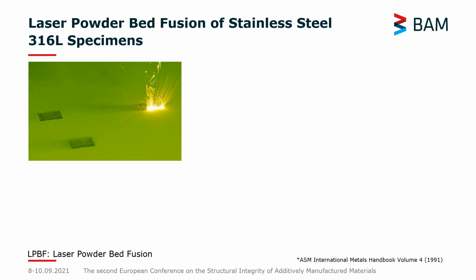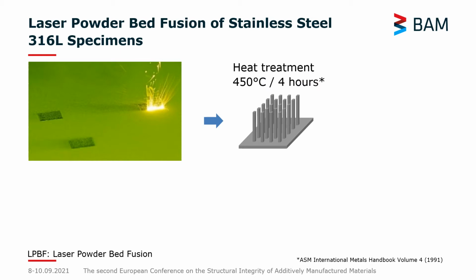For this study, we manufactured our specimens via laser powder bed fusion and left them on the build plate and heat treated them at 450 degrees for 4 hours. We did this for two reasons. One reason was that we wanted to relieve peak residual stresses to prevent any sort of distortion once we cut the specimens off from the build plate. The second reason was that we wanted to maintain the microstructure that is characteristic for laser powder bed fusion.